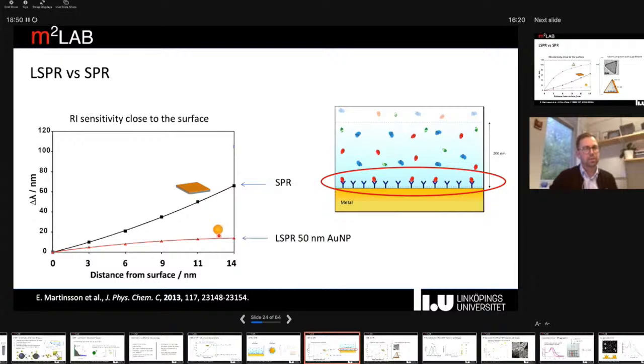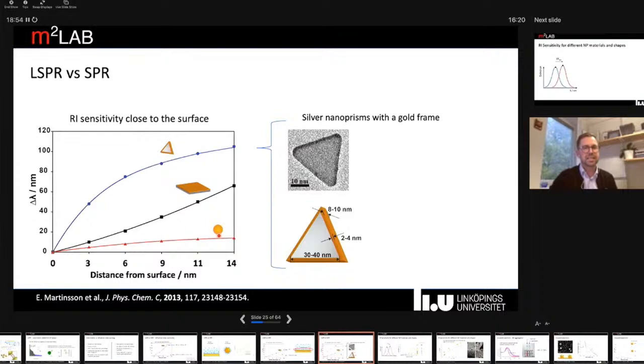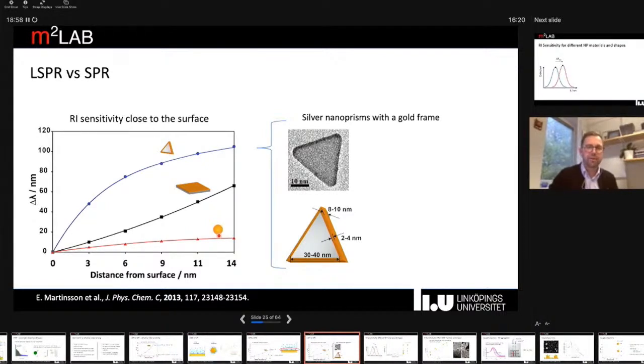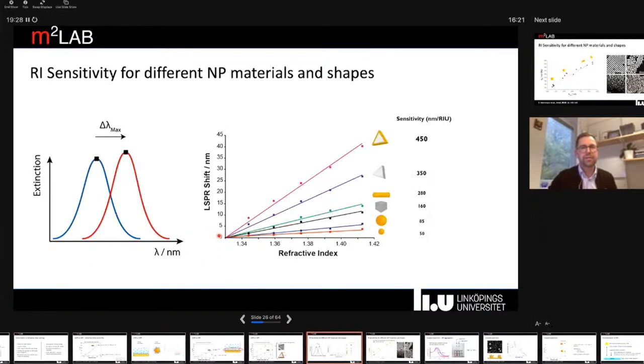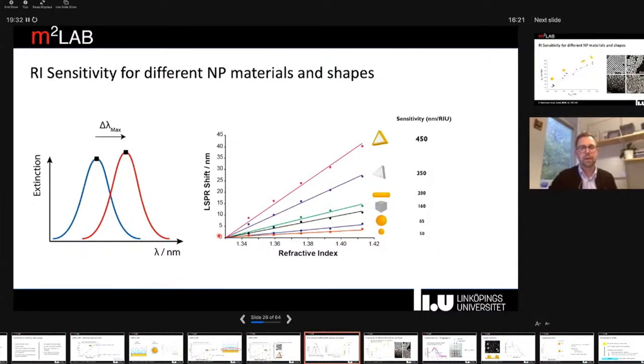And by using some more sophisticated nanoparticles, such as these gold nanoframe protected silver nanoprisms, we can actually outcompete SPR, at least within the first 20 nanometers or so from the surface. So obviously, we have quite a large dependence here, as you can see, of the refractive index sensitivity on what kind of particles we use. And we can compete with SPR in this instance. So these gold frame silver nanoprisms are relatively good with respect to sensitivity. But we see that there are also other particles that can perform rather well. Some are less complicated to synthesize as compared to these prisms.